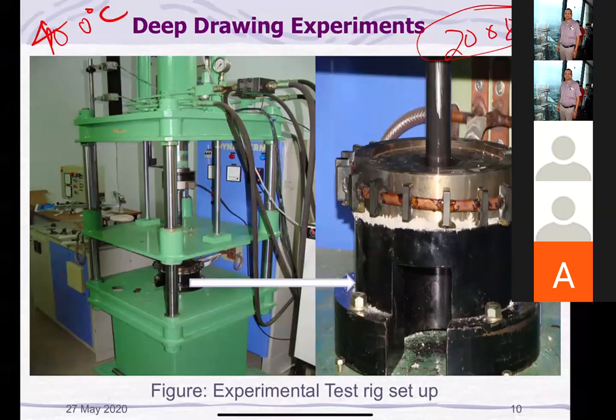Now see, these are induction coils to heat the die, because the problem is that even if you are heating the workpiece, if you keep it on a cold die, again it is going to be thermal shock. So that should not happen. The workpiece we keep here, and the punch basically deforms the material, and the drawn component will come out from this side. See, this is another induction furnace, and here we keep the workpiece. We heat it and shift it over the die.